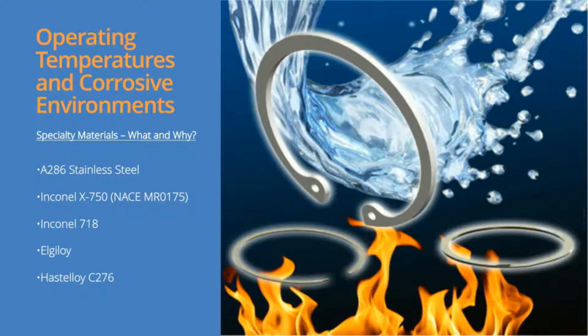So you can have 700 degrees Fahrenheit for a max and be NACE compliant, or you can be at 1,000 degrees Fahrenheit for your max and not be NACE compliant. Inconel 718 is great for corrosive environments, not NACE compliant, and will withstand temperatures up to 1,300 degrees Fahrenheit. Elgiloy is NACE compliant, and 800 degrees Fahrenheit is a good maximum for that one.